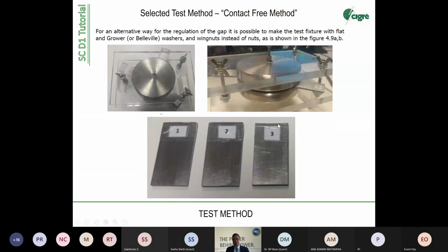Contact-free method, this is how it looks. So this is a test arrangement. And what you see in the upper right picture is the setup of the gauges. So the 3 is a gauge that is used here for control of the distance between the electrodes, which is a challenge, because, as we see later in the sensitivity analysis of the error mode analysis, the spatial geometrical conditions are essential for the quality of the results. It means if you have a non-parallel arrangement of the plates, this may affect the results. The distance has a tremendous impact on error. Also, area measurement and thickness measurement of the sample itself are contributors to errors.